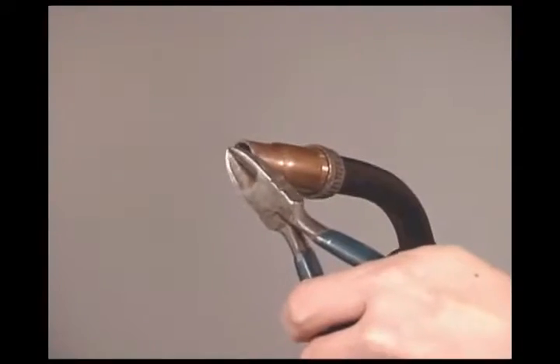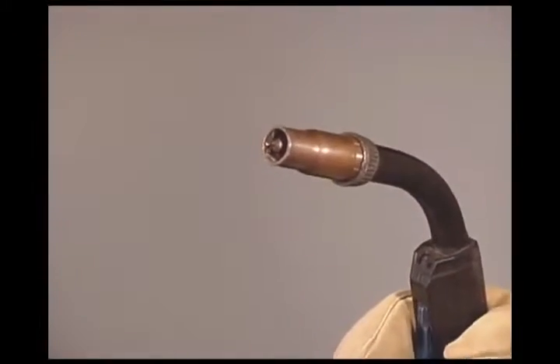Excessive gas flow may have a cooling effect on the weld puddle, and if there's not enough gas coverage or you lose the shielding gas for some reason, gas pockets called porosity will form in the weld bead. With the flow meter set, snip off the excess wire and you're ready to do some welding. This is industrial equipment, and even the smaller welding machines are well built, but part of wire feed welding is keeping the wire feeding smoothly.